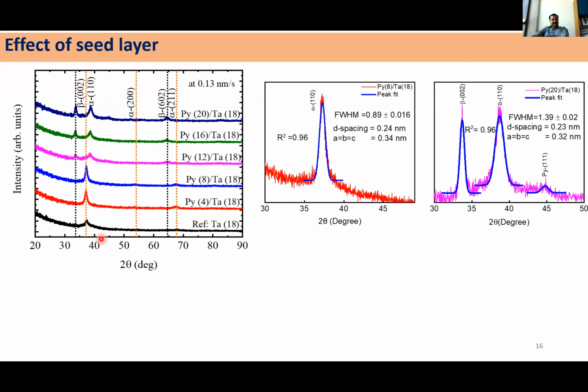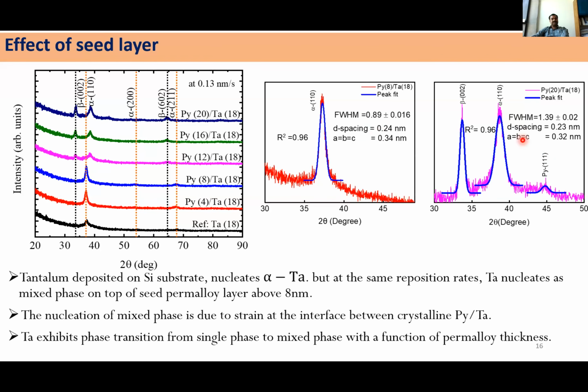And we wanted to see why this is happening. If you clearly observe, you can see that there is a shift in the 2 theta for the alpha peak. So basically, when tantalum is deposited above 8 nanometer, we can clearly see that the lattice parameter has reduced, which means that there is a strain coming at the interface between permalloy and tantalum. And it is obvious that permalloy can grow as a crystalline layer. So there is always a possibility of strain because of the lattice mismatch between the permalloy and tantalum. That has caused a change in the d-spacing and also the lattice parameter, right?